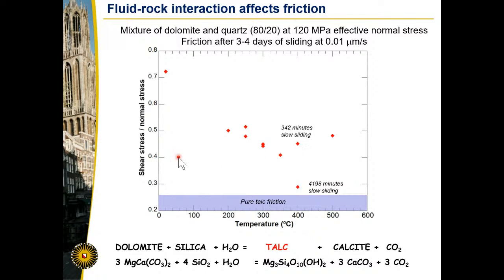much higher. So I infer from this data that it suggests we have this mineral reaction going on in our experiments. We have dolomite that is reacting with quartz and water, and it's forming this frictionally weak mineral called talc, plus some calcite as well as CO2.